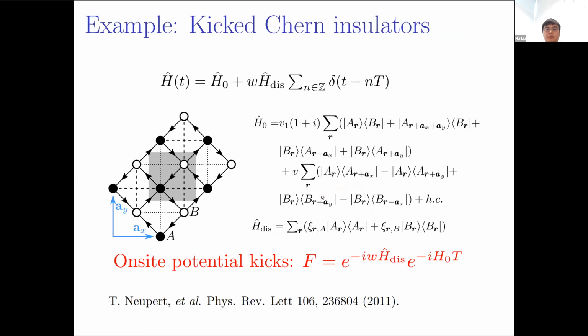Okay, so to show this process, we give a concrete example, the kicked Chern insulators. The time-dependent Hamiltonian have two parts. The static part, H0, it is composed of the nearest hopping and the next nearest hopping. Along the arrow line in the left panel this represents the nearest hopping along the arrow line. The nearest hopping strength would pick up a phase factor e^{i pi/4}. For the next nearest hopping, we have two forms. Along the dashed line, the next nearest hopping strength would be V, but along the dotted line, the next nearest hopping is minus V. So the second part of the time-dependent Hamiltonian is the on-site potential kicks.